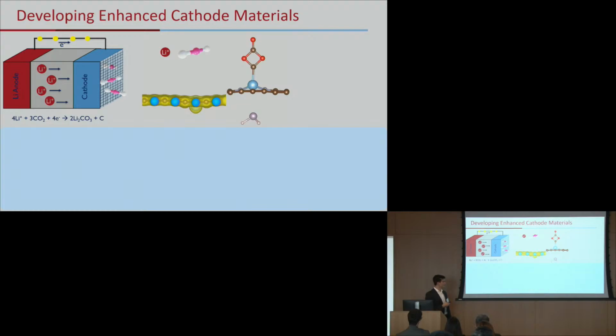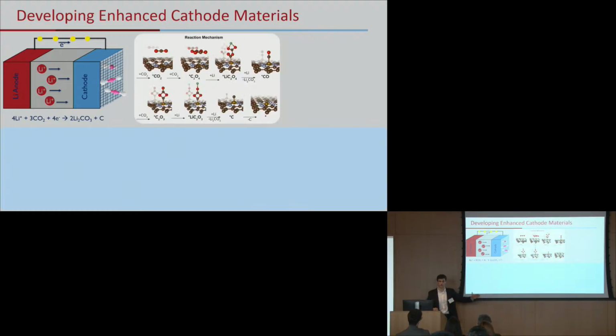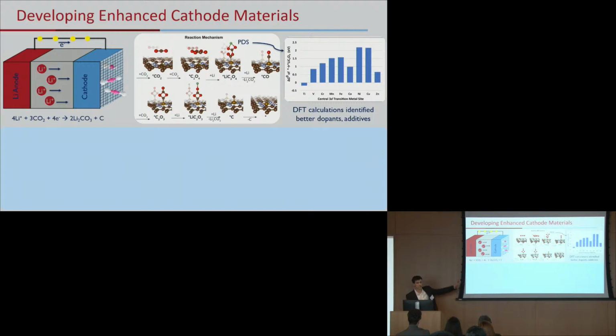And from our first results, by getting an entire reaction mechanism, we found that if we just change the dopant from iron, which other papers used, to a different transition metal, the potential determining step was lowered significantly. So already there, we have a super exciting result. It's like, okay, experimentalists, here's how we can make a better battery. Maybe we want to try this out in an experiment. Awesome result. But this isn't what's most exciting about this kind of field. It's the fact that we can look deeper. And we can look at the actual physics and chemistry of what's happening here to determine how we can extrapolate to new materials, new catalysts, and new energy storage solutions.